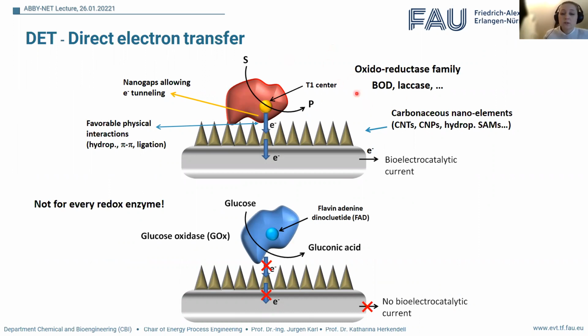For example, bilirubin oxidase, here abbreviated BOD, or the redox enzyme laccase, have the ability, on carbonaceous nanoelements like carbon nanotubes, different carbon nanoparticles, or self-assembled monolayers, to partially unfold on these nanostructures, which gets them sufficiently close to have very fast and effective electron tunneling between the active center and the electrode surface. This is hypothesized to be based on hydrophobic interactions, or so-called pi-pi stackings or ligations. Now, the sad thing about this very efficient wiring mechanism is that most other enzymes cannot do it.